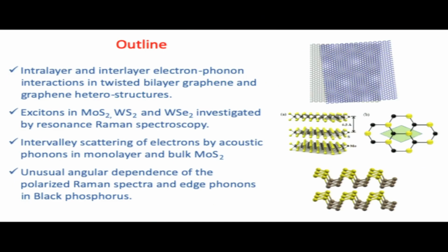I will talk mostly about those three systems here. One is two layers of graphene that are twisted. This is a very hot and new topic because it was found recently that when you have a specific magic angle, there is superconductivity when you have only two layers of graphene that are twisted by 1 degree. Then I will talk mostly about electron-phonon interactions in this talk, and I will show that in the case of twisted bilayer graphene, we can have intralayer and interlayer electron-phonon coupling, which connect electron-phonon in different layers and in the same layer.